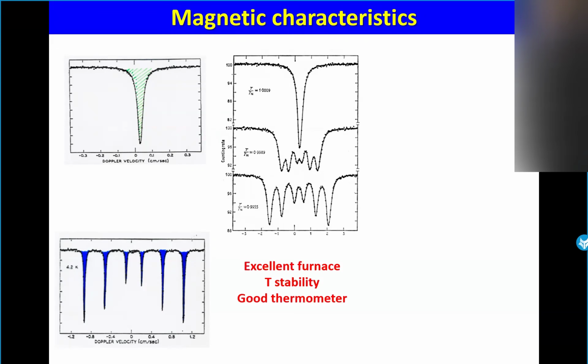So that means you need an excellent furnace and an excellent thermometer, because you have to stabilize for a long time, at least 5 or 6 hours at exactly the same temperature, to get a good Mössbauer spectrum. And you can see that the resolution is perfect.